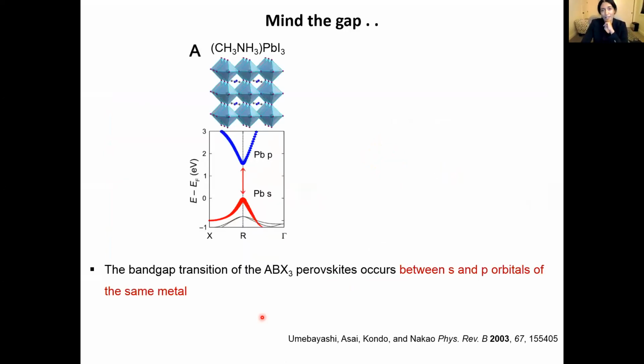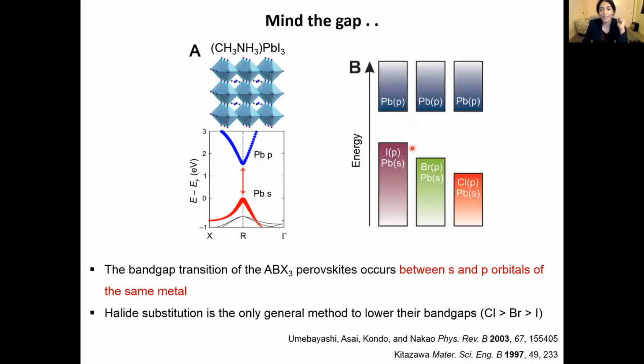So first, we should always start with something familiar, so we can look back at the lead iodide perovskites. And here I'm showing you a simplified band diagram of this material, where I'm highlighting the metal orbital contributions. So the valence band has lead 6s character, the conduction band has lead p character. So the band gap transition is an electron going from an s orbital to a p orbital on the same lead. And at some level, these orbitals are fixed, right? It's the same atom. We can change the halide, and this halide changes mostly the valence band, and that allows us to tune the band gap to some level, which is useful.